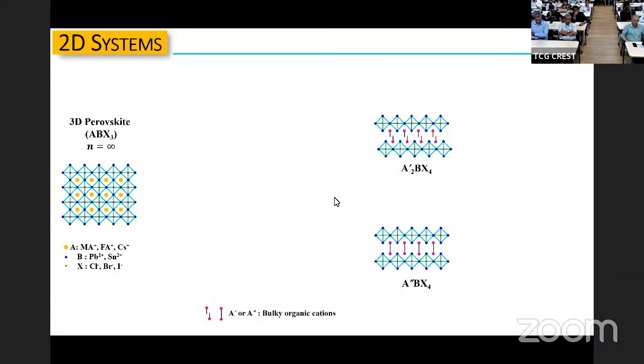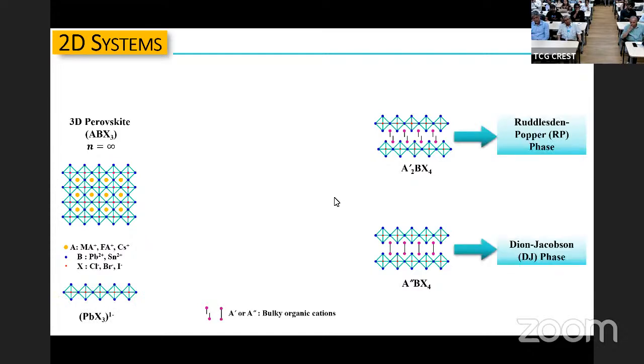This again is systematic because actually it's even more exciting than that. I only talked about that you can put molecules here, split it open, but that splitting open can be in two different ways, with one organic unit that couples at both ends. So think of it as a two-headed object. One head will couple to this, other head will couple to that. And then you can see that this inorganic unit and that inorganic unit will be exactly above each other. But if you have a single-headed organic molecule like this, then it will split open there, that will split open there. But these molecules will try to interdigitate themselves for energetic reasons, and therefore they'll stagger each other, so this one will be shifted with respect to that and give rise to another structural family. This is called Ruddlesden-Popper series, and this is called the Dion-Jacobson. So there are two different kinds of structure.